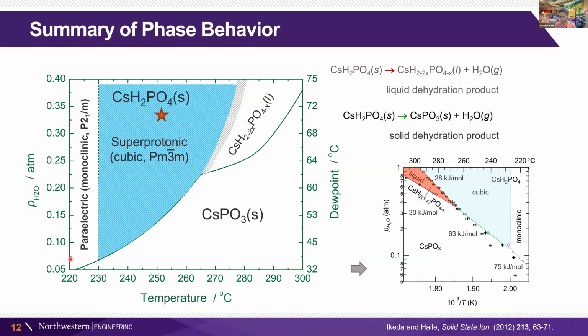So it all makes thermodynamic sense, and we understand this material, and we have a very good roadmap to the conditions under which we can use it in our fuel cell. And what you see on the left is the red mark that shows the typical operation conditions for us. So we're typically at 250 degrees Celsius, maybe a little bit lower, maybe 240, and we humidify to a level on the order of 0.3 to 0.4 atmospheres. That means that it is a 100% humidification at around 70 to 75 degrees Celsius.